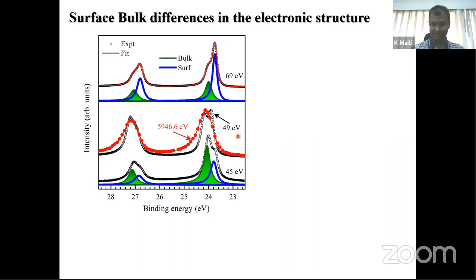Normally, in many materials, if you look at the effective surface depth, that goes or extends beyond 2 to 3 layers, or 4 layers sometimes. Like if you look at transition metal systems, there can be of the order of, say, 10 to 12 angstrom.